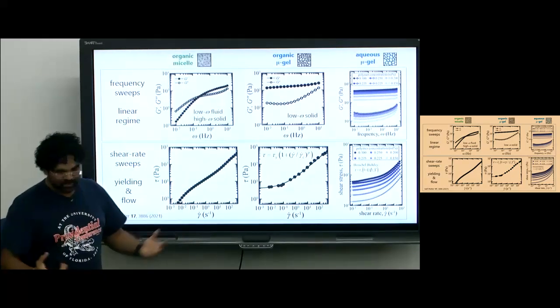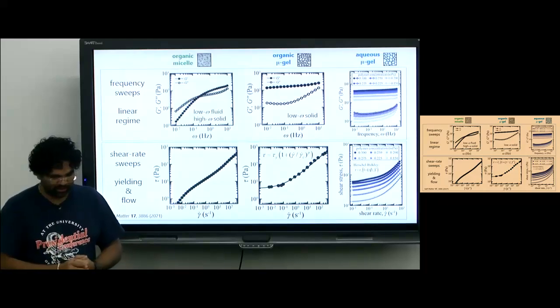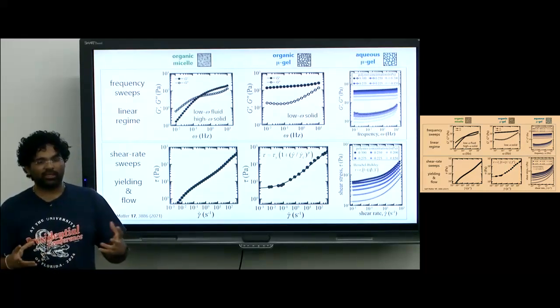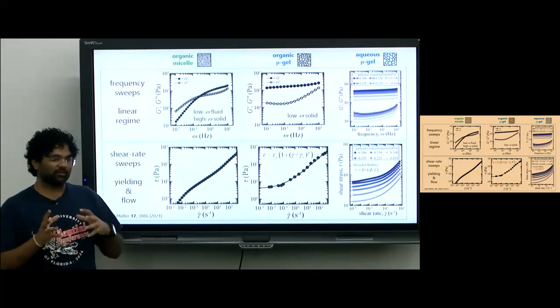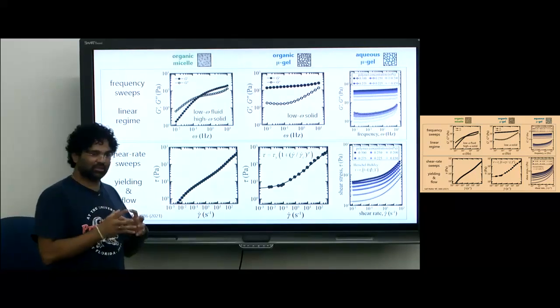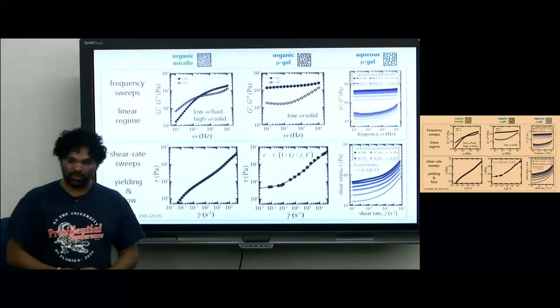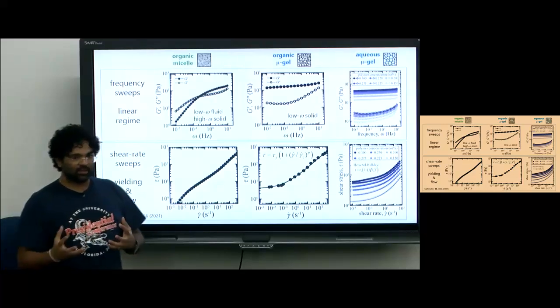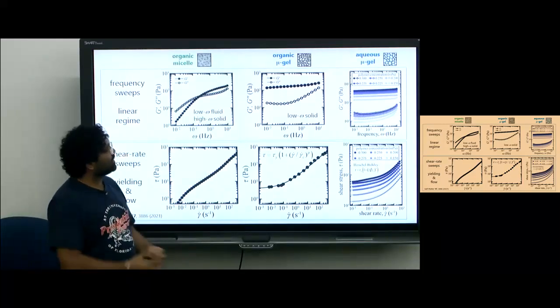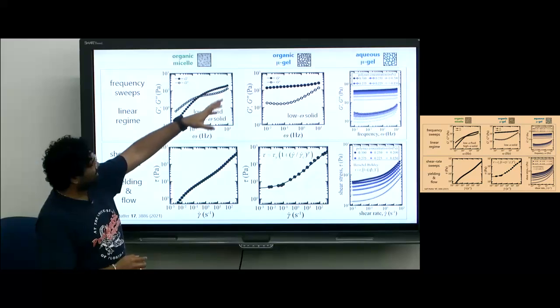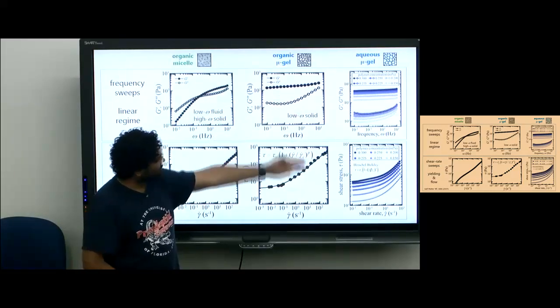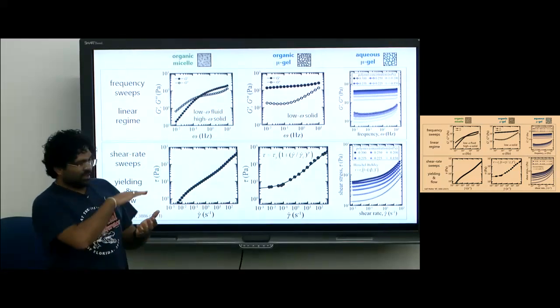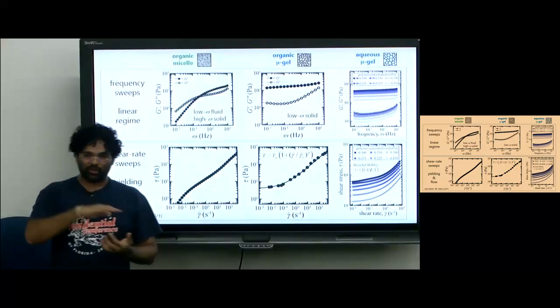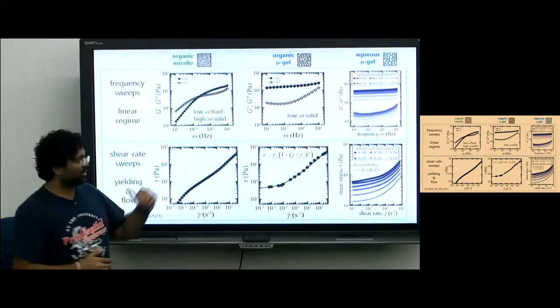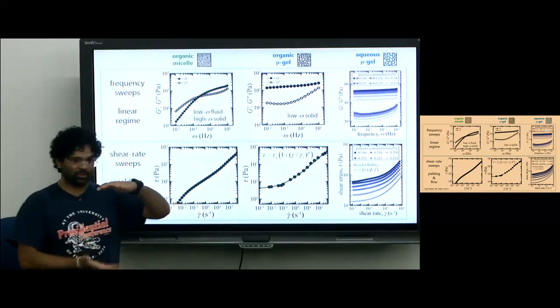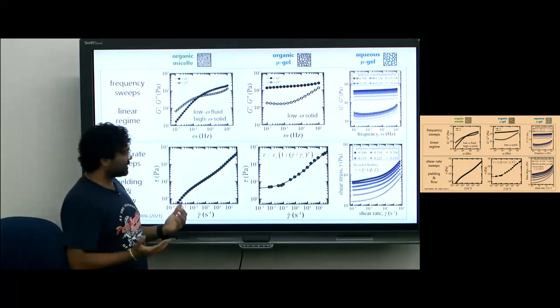In the regime of soft fluids, especially in shear rheology, modulus is considered as a complex modulus. The real part is considered as solid-like behavior, which is G prime, called the storage modulus. And the imaginary part is considered as the viscous component, which is the viscous modulus, G double prime. For example, in the plots on the rightmost corner, if there is a weak frequency dependence for the storage modulus, it's considered an elastic solid. And also if the storage modulus is above the loss modulus, it's considered an elastic solid.